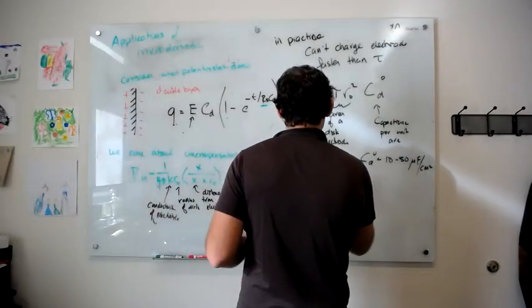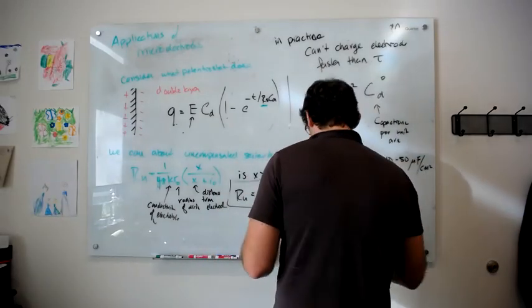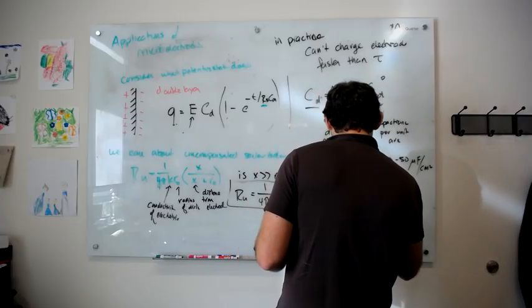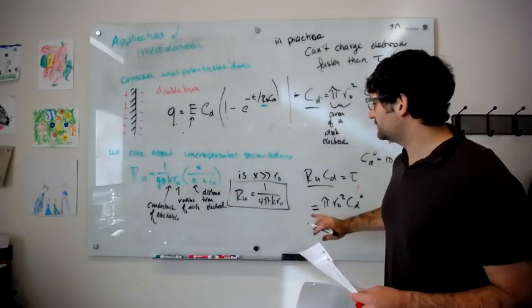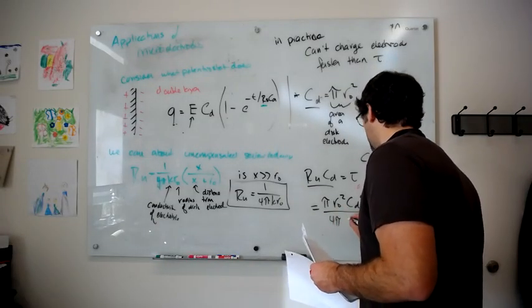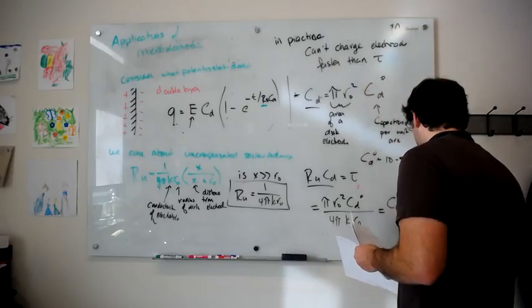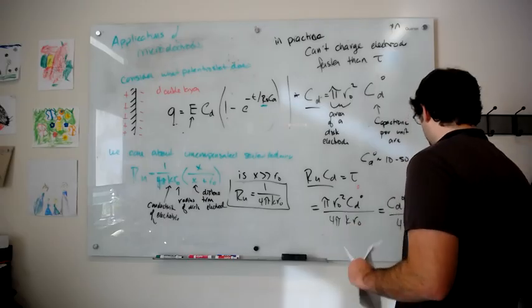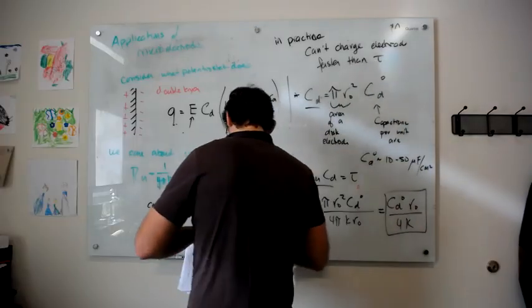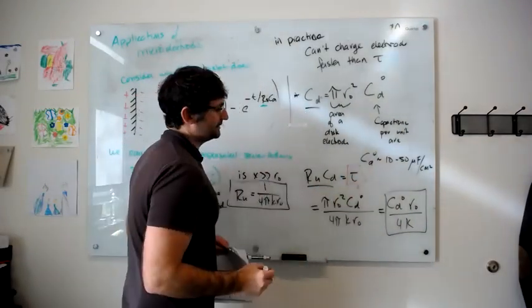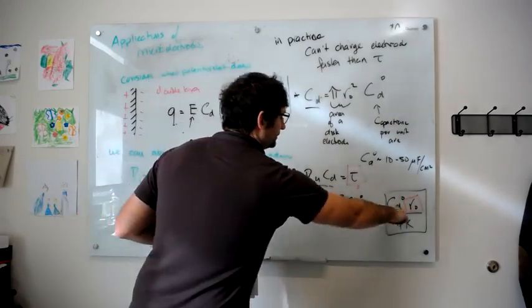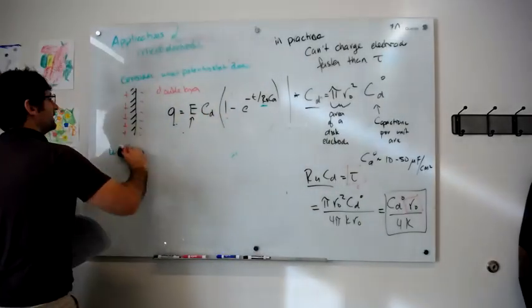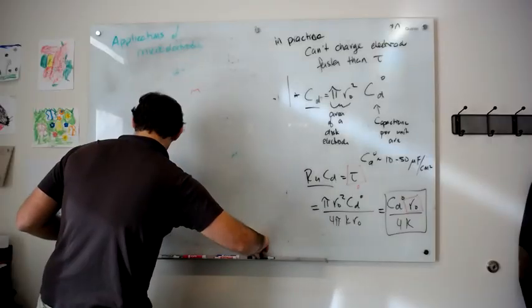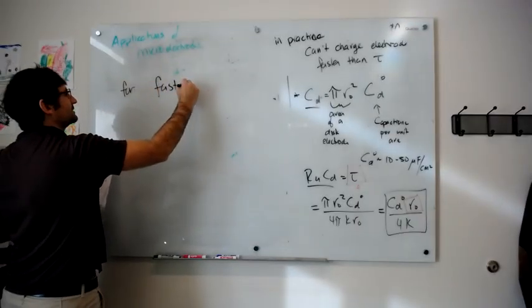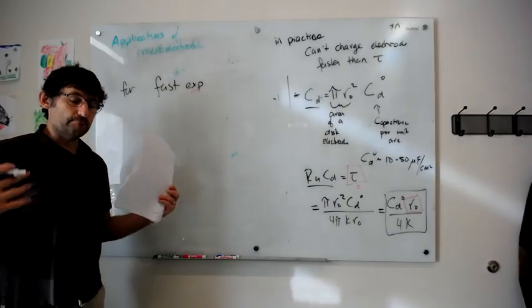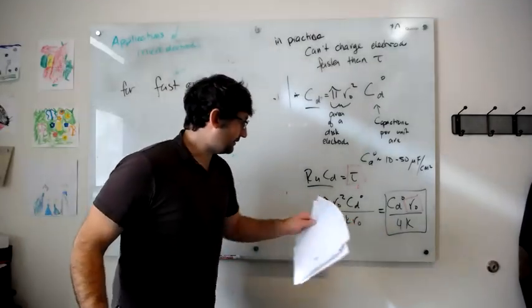And I can calculate RuCD, the time constant for this cell, as just pi R naught squared CD naught, this equation here for the capacitance, times the uncompensated series resistance, 1 over 4 pi kappa R naught. Cancel terms and get CD naught R naught over 4 kappa. And what you can see is this time constant tau, so how fast you can do an experiment, can be made arbitrarily small by making your electrode very small. These are all constants. Of course, you also want a very conductive electrolyte to minimize the uncompensated series resistance. So for fast experiments, say you want to measure something on a microsecond time scale, you can do that if you use a micro or nano electrode.